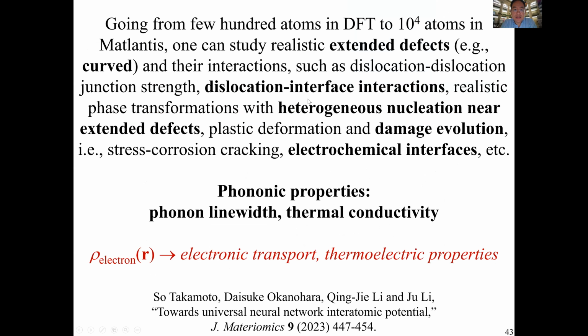So what this will enable us to do is to study microstructures. Because traditionally when you do DFT, if you do a grain boundary or surface, it's typically flat, or if you do a dislocation, it's like a straight dislocation core. Now we can study dislocation-dislocation junctions. We can study curved dislocation, curved interface interactions. We can study realistic phase transformations with heterogeneous nucleation, plasticity, damage evolution, things like stress-corrosion cracking, electrochemical interfaces, and so forth. And we have been working very hard on representing the phonon properties well. Phonon is a bit tricky because it's like a second derivative of the energy.